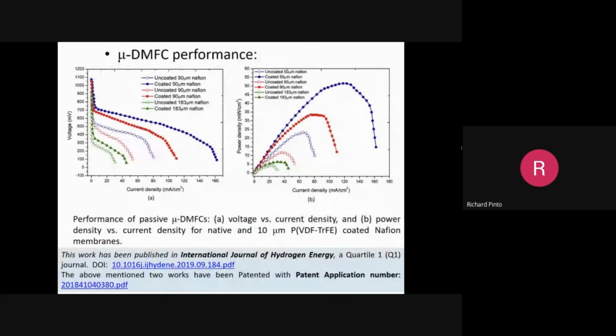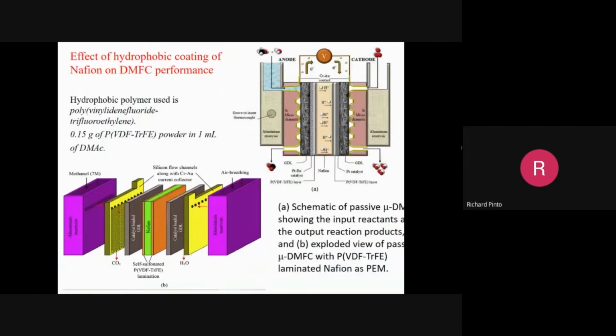Now, this is one more work we did, to increase the power density by reducing the methanol crossover. These plots are repeated again, but I won't go into detail. Let me explain what happens. We use a PVDF TrFE coating. Here, this is shown correctly: platinum ruthenium catalyst on the anode and platinum catalyst on the right side, the cathode side. This is again an exploded view.